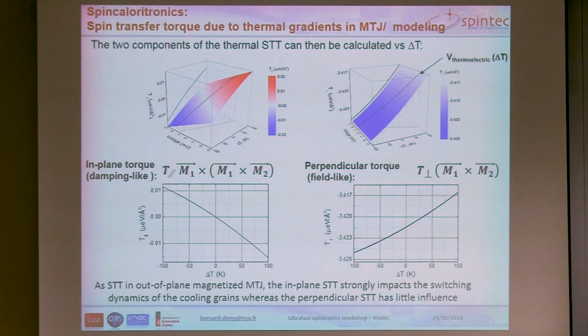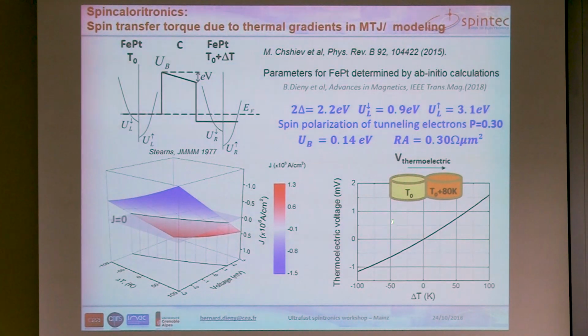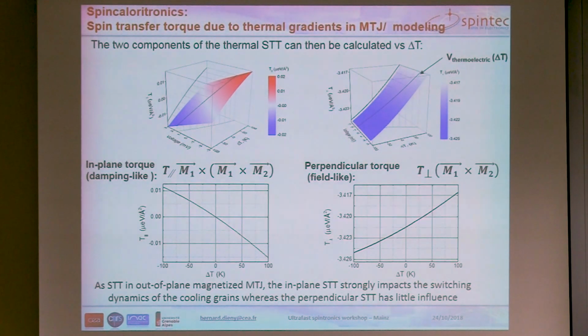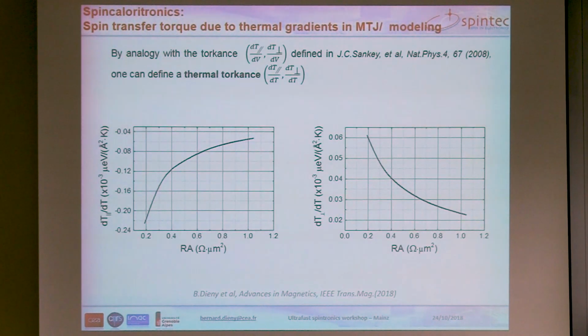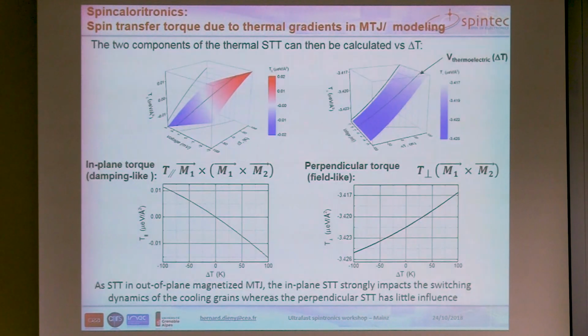And so by using the relationship that we determine here between the thermoelectric voltage and the difference of temperature, we can actually extract the in-plane torque and the perpendicular torque as a function of the difference of temperature between grains. And so for 80 Kelvin, we would have this negative value here for the in-plane torque and this value for the perpendicular torque. We can also define a torquance, which is defined as the ratio of the derivative of the in-plane and perpendicular torque with respect to the temperature. But at this point, I'd like to point out that the in-plane torque, the main one, is negative. This is what we see here. We have a negative torque for positive variation, plus 80 Kelvin difference.